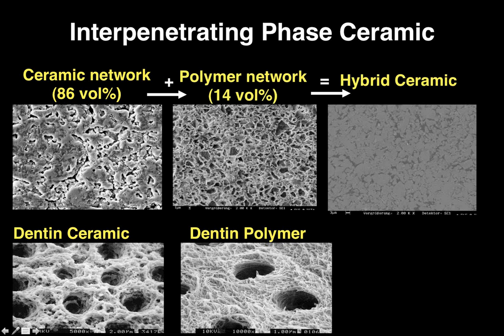So what do we have? We have our ceramic by volume, 86%, and volume percent is how you really want to look at these structures. I know manufacturers often talk about the composite resins having 86% or 85% ceramic. That's by weight. The ceramic weighs a lot more than the polymer, so it's easy to get a very high number when you're talking by weight. It's not easy to get a very high number when you're talking by volume percent. So most of the material of Enamic is a ceramic with a small amount of polymer to give it resilience, improved machining properties, improved homogeneity, able to mill it to thinner structures than you would get with a traditional ceramic.